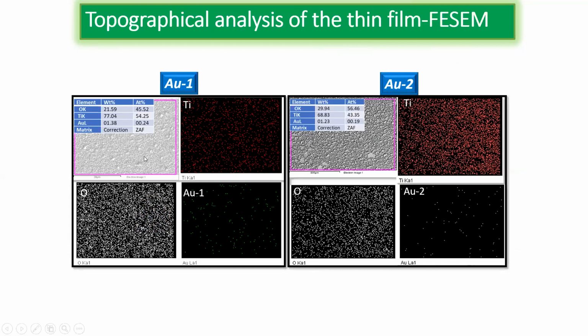By using SEM EDAX, we see how it has been uniformly dispersed. This is a TiO2 thin film, and in the mapping we see that my gold nanoparticle is uniformly dispersed and is in a really very small quantity compared to the titanium. So this is around 1 to 2%. This is exactly 1.38%, of the nanomaterial we have dispersed.